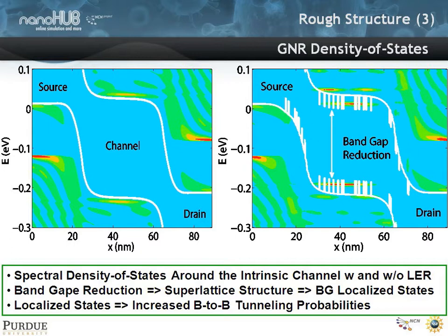You see that for electrons and also for holes, because the dispersion for electrons and holes in a graphene sheet are the same. Now, if you statistically roughen the line edge, you have a superlattice-type effect and you narrow the gap locally. You start to confine states into that superlattice — here's a ground state, an excited state to the right, and a third state on top. You have confined states sitting above the gap in the superlattice, and you will tunnel through them resonantly. This means the gap is narrowed, and if the gap is narrowed, you increase the current.